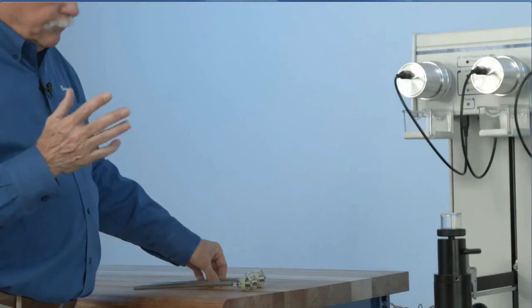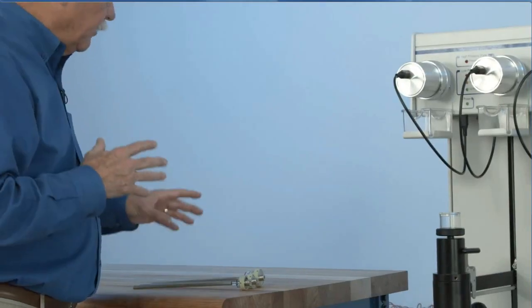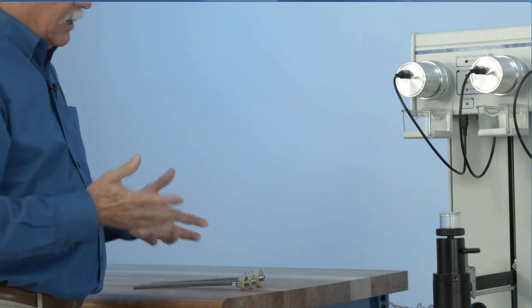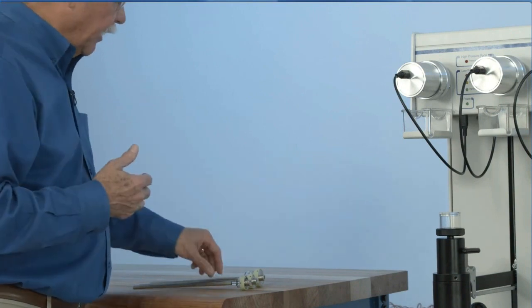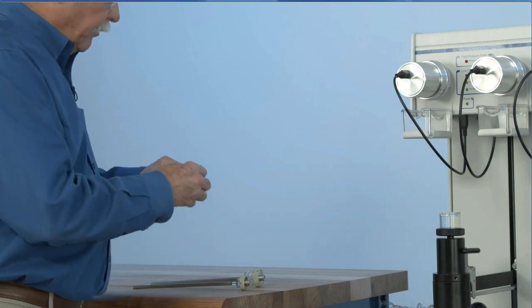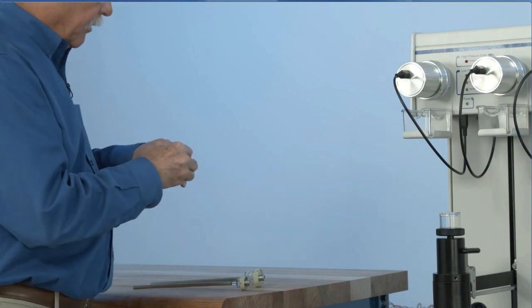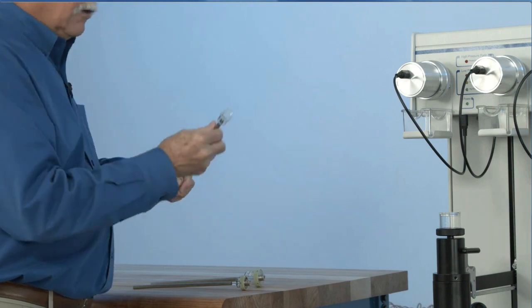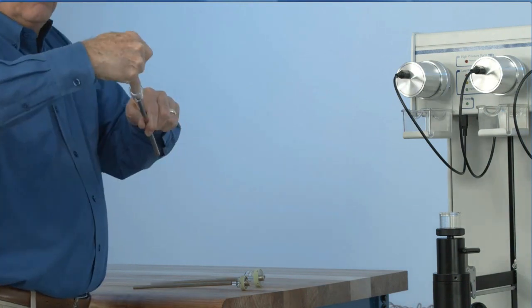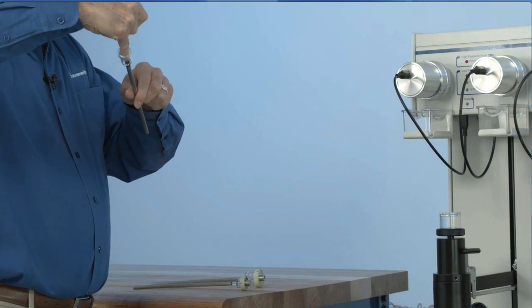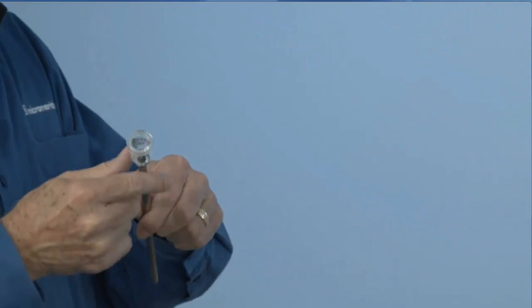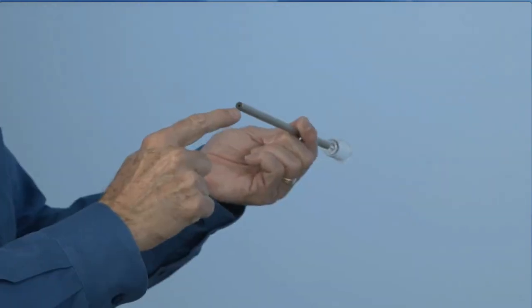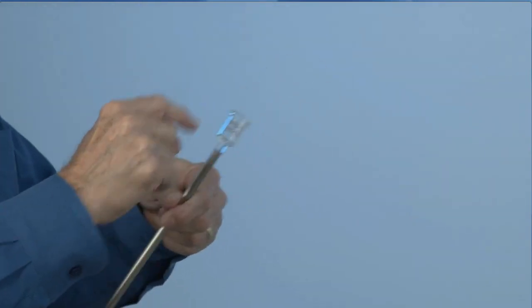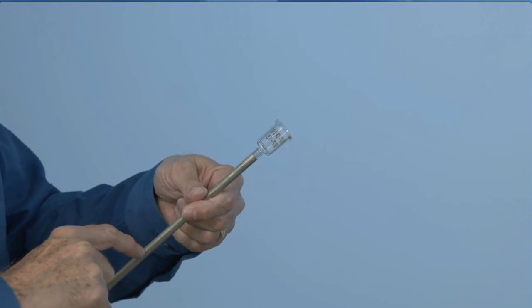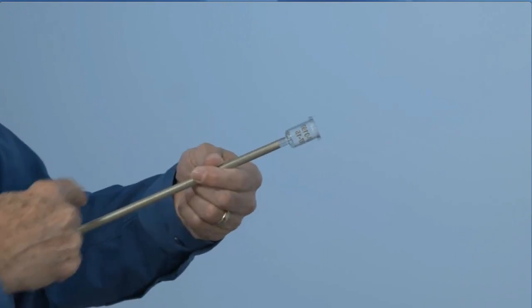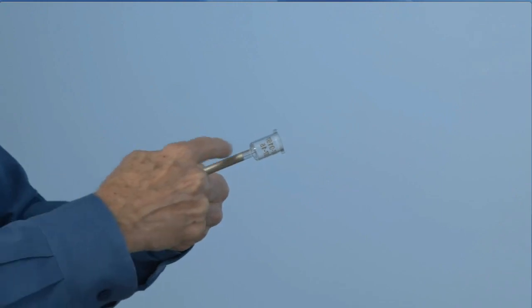Okay, speaking of sample holders, we do have 19 standard penetrometer configurations for samples of different types and different sizes with different porosities. This one has a cup volume here of 5 cubic centimeters. And you'll notice that it can hold a large monolith type sample because it's a nice open cylinder inside there. This one happens to have a very small stem volume so that if our sample's not very porous, we'll still use a significant amount of the mercury available. The mercury available for the analysis is what is inside this metal clad area. And when we talk about the software,